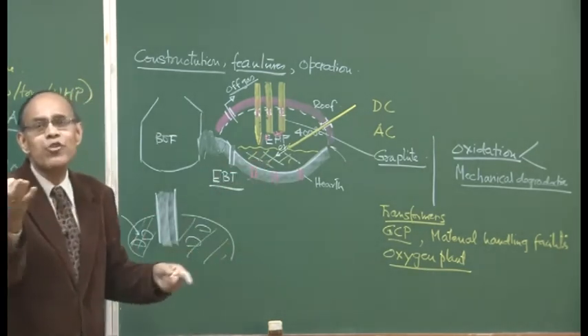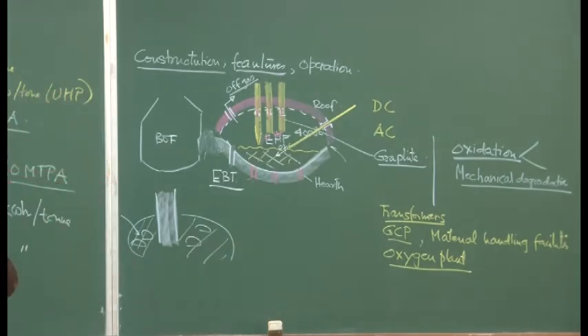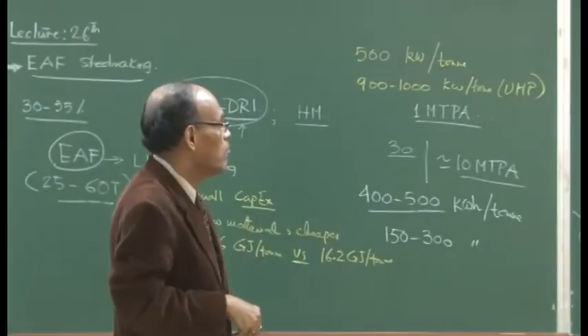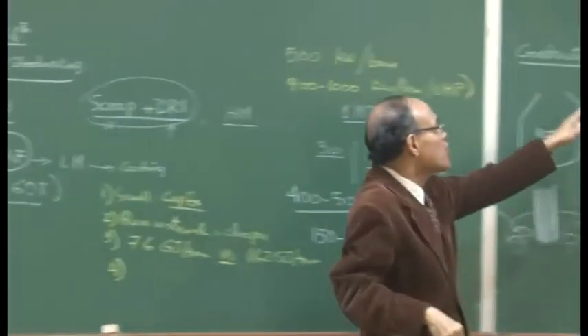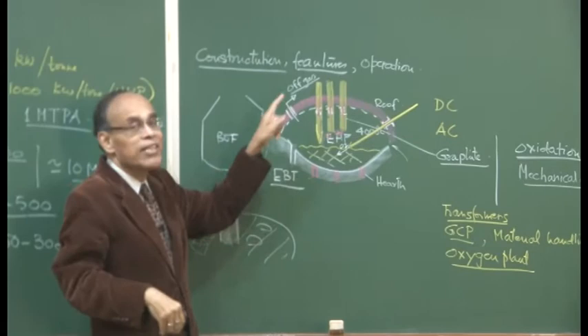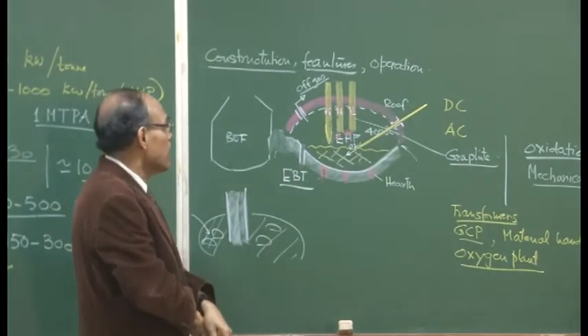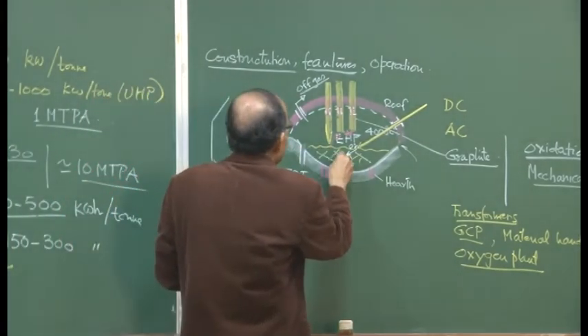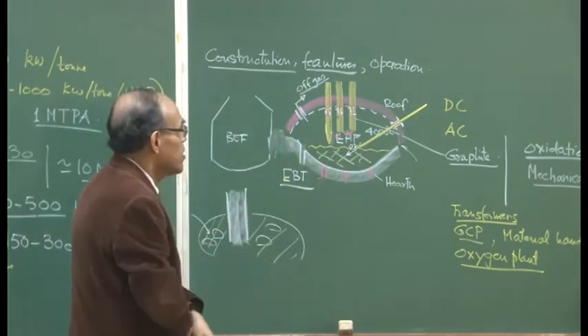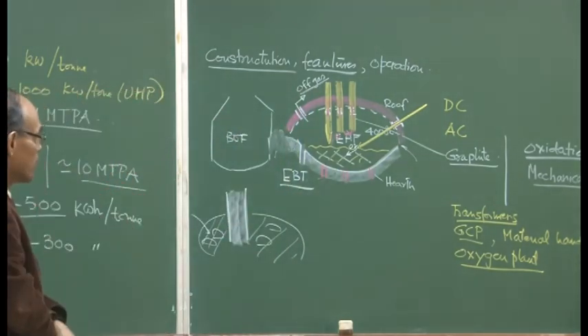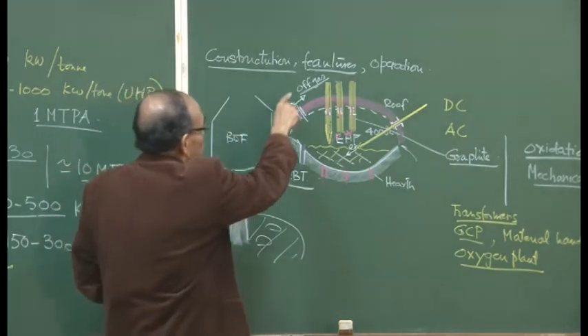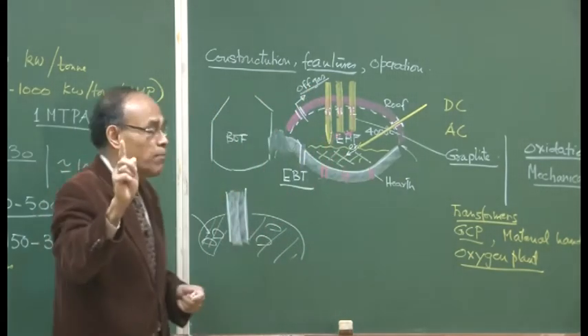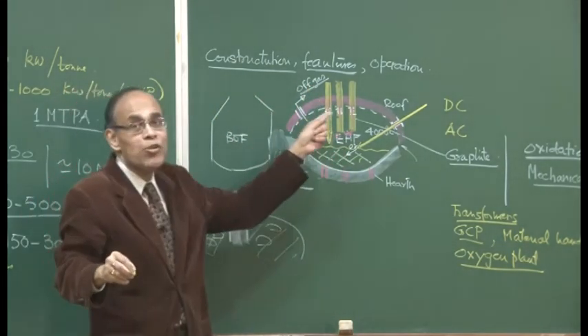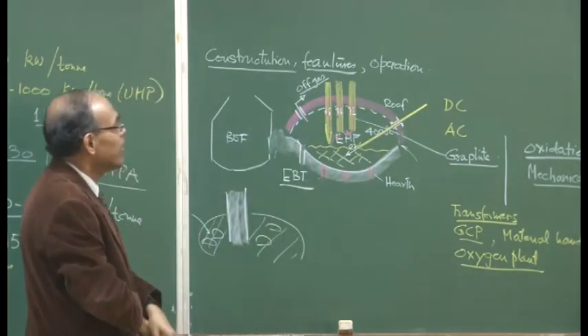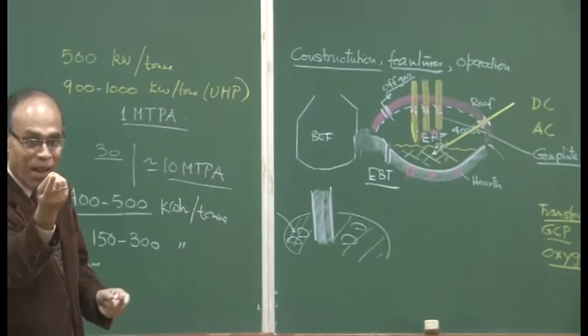Another modification you can visualize is that you are not charging scrap at room temperature, but you are preheating it using this off gas which goes out at a very high temperature, because the furnace environment is 1600 degrees centigrade. So, it can go up to 600, 700 degrees centigrade for sure, and this heat contains sensible heat, particularly the sensible heat can be used to heat the scrap itself, and that scrap can be directly fed,